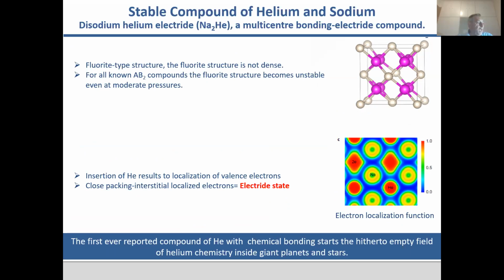Even conventional AB2 compounds show phase transition under pressure. So the idea here is why this phase becomes stable at very high pressure. The solution is that in reality, we don't have a bonding just between sodium and helium. We have a multi-center bonding that includes sodium, helium, and localized electrons. So in reality, we have an electride plus some ionic interaction between sodium and helium.